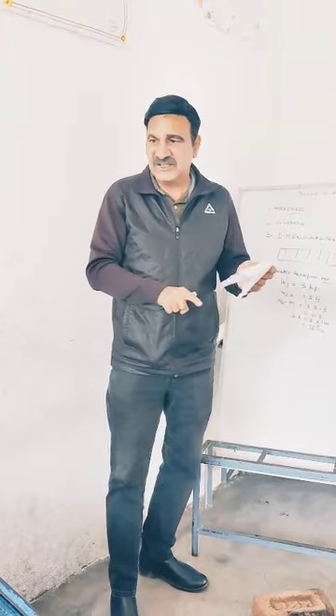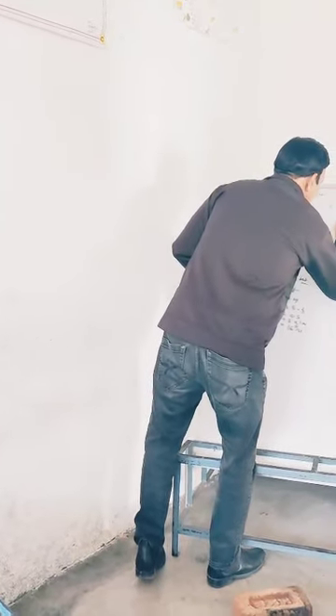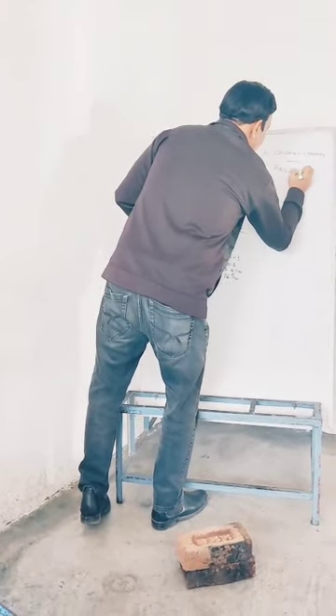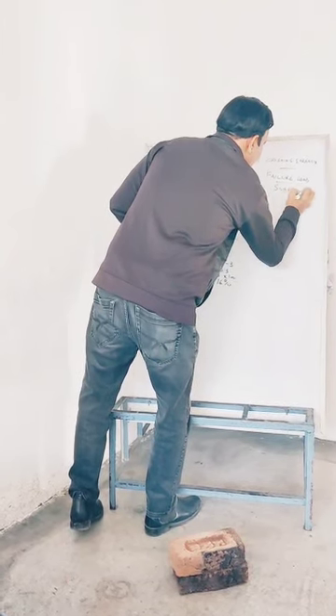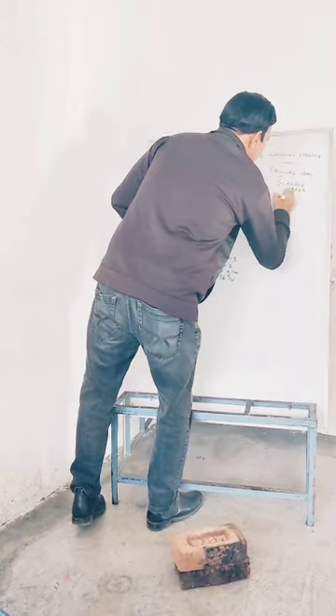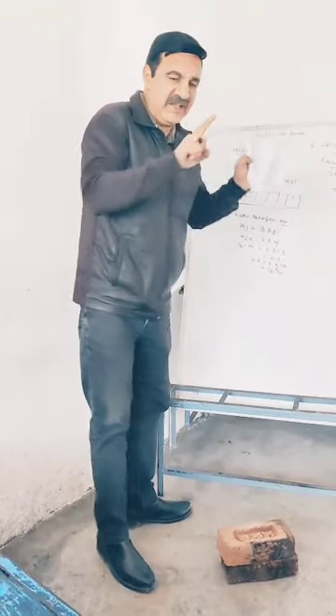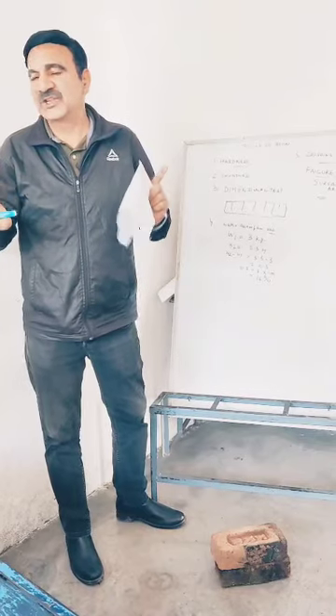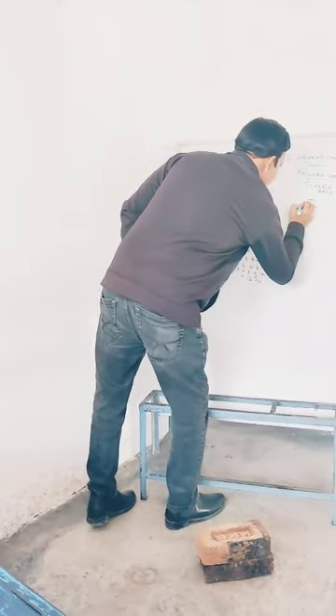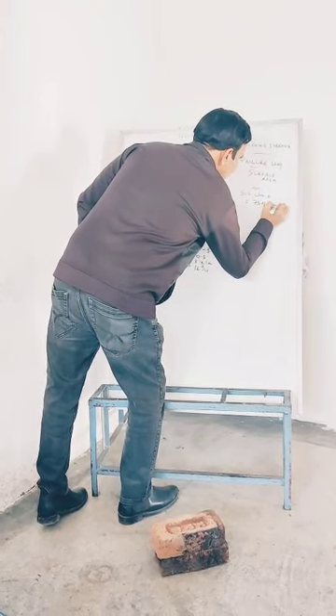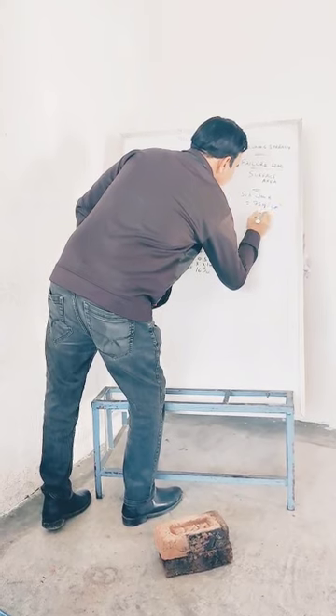and we see when it fails, that failure load is seen. Failure load divided by surface area of the brick will be the compressive strength. When this brick fails in that compressive testing machine, that failure load divided by surface area will be the compressive strength of the brick, crushing strength. Normally subclass B bricks have 75 kgs per square centimeter crushing strength, and subclass A has 100 kgs per square centimeter crushing strength.